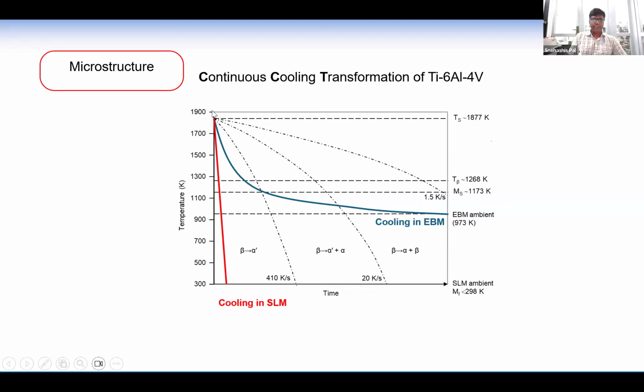In selective laser melting, the machine temperature is mostly like room temperature, or maximum 100 degrees. It can increase slowly, but the cooling rate is very high, like a quenching. So the melt pool or the whole part cools down very fast. That's why the microstructure differs from electron beam melting to selective laser melting.